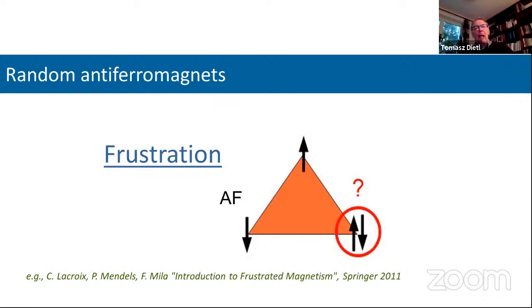And I already said that we have no ordering despite the strong coupling. And here is another notion which is important in many systems, but also in random antiferromagnets, which is frustration. So we have very strong antiferromagnetic interaction between spins, but the spins are frustrated, and actually we do not observe antiferromagnetic ordering because of this frustration.